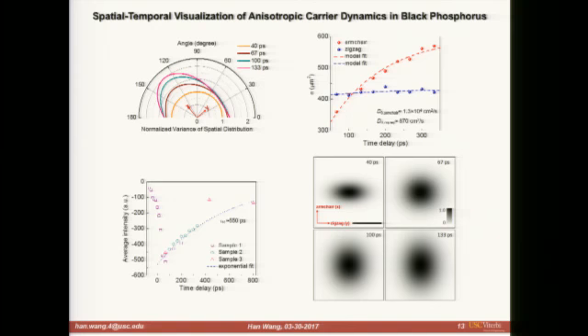And we can also extract, for example, the carrier recombination time, which is 550 picoseconds in this material, and the diffusion length, the recombination length, is about 9 micrometers along the X direction of the crystal. So these are all very useful information if we were to build these optoelectronic devices.